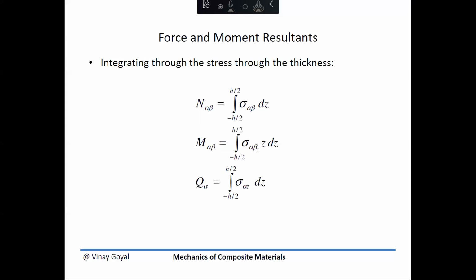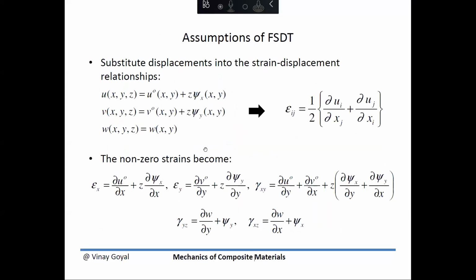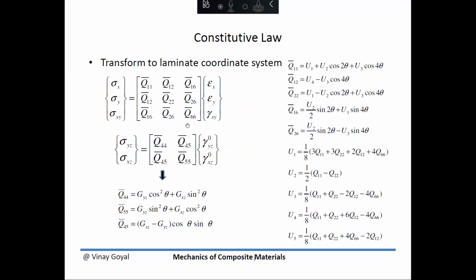MXY, sigma XY. We have also now transverse shear terms, QX, sigma XZ, QY, sigma YZ. So these have been integrated through a thickness. And the reason we're doing that is because we have reduced everything to the mid surface so we can track the mid surface alone. By doing so, we have simplified 3D structures into a structural model that accounts for tracking the mid-surface alone. We've simplified the problem by making the deflection assumptions an explicit function of Z. So that's quite convenient approach that we came up with.